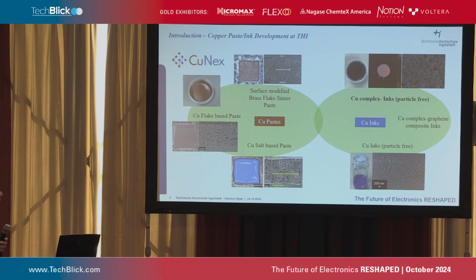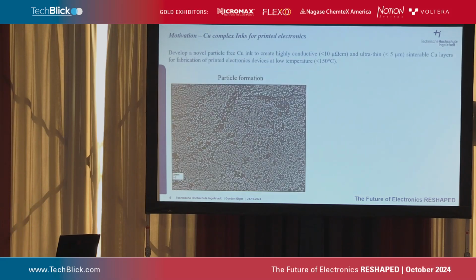Therefore, today I really want to focus on the inks. There we can distinguish particle-free inks, where you just use a solvent which dissolves the metal salt, and the metal salt is copper formate. You can search for other salts, and we are doing it, but in the end we always come back to the copper formate. However, there is not very much copper formate dissolved in any organic liquid. Therefore, the approach we are using is a complex ink, where you use a complexing agent to reduce the decomposition temperature of copper formate for sintering. You can also mix those two together to create hybrid paste, which have metal particles, copper flakes, and metal salts. Okay, what is the problem?